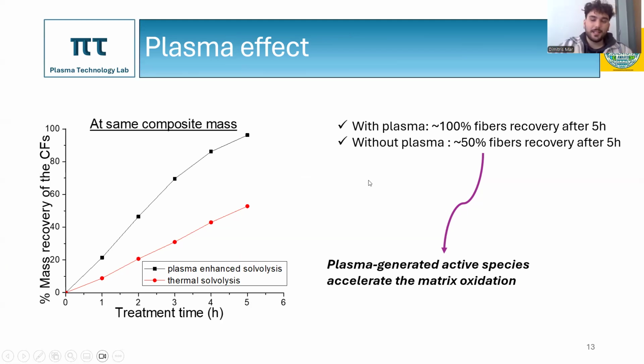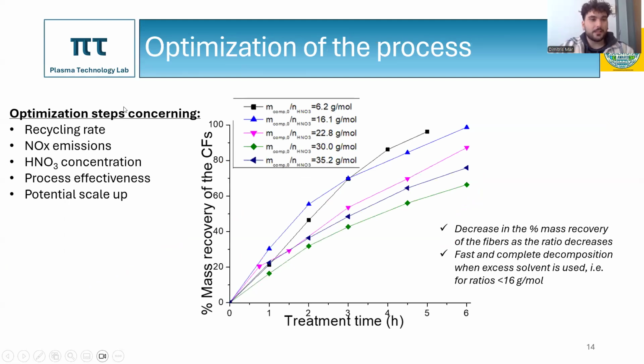After we established that, we wanted to optimize our process. That's why we had some optimization steps concerning the recycle rate, the emissions, the concentration of the solvent, and the process effectiveness, so it can lead to potential scale-up. For example, in this graph, we try to maximize the amount of composite mass that we can decompose with a specific amount of solvent. That's why we studied the ratio between the composite mass and the moles of the solvent. From this graph, we saw that there is a decrease in the percentage of mass recovery of the fiber as this ratio decreases, while fast and complete decomposition can be achieved when excess solvent is used, for ratios below 16.